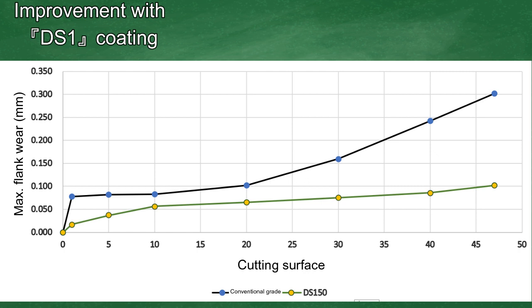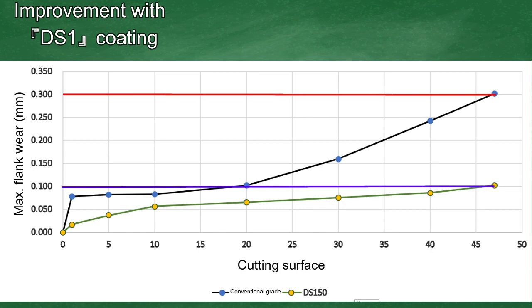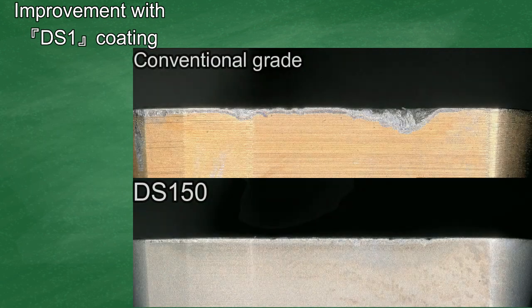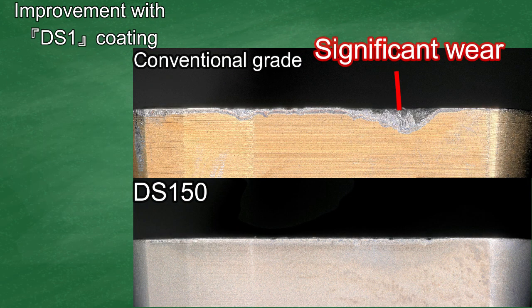When machining 47 surfaces, the amount of wear is reduced to about 0.1 with the DS1 coating, compared to about 0.3 with the conventional product. The difference in wear is clear in the photos and shows the high performance of the DS1 coating.